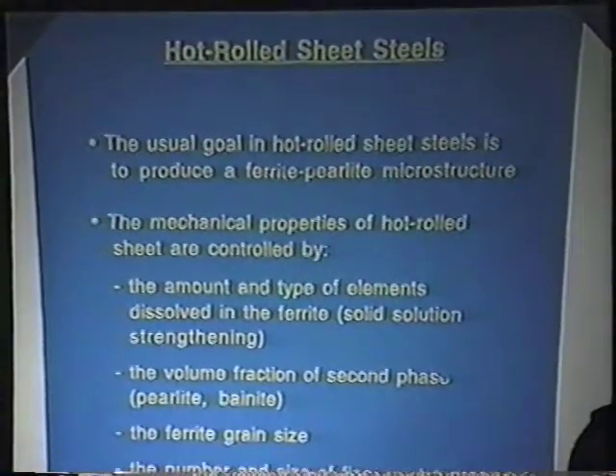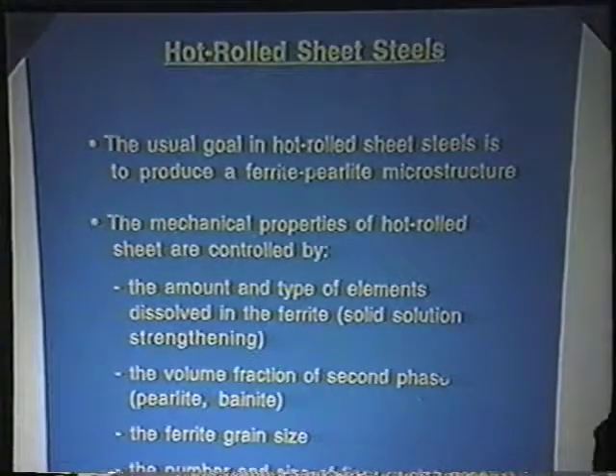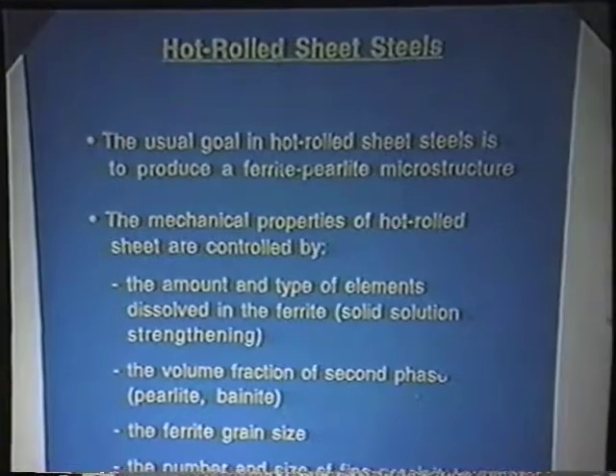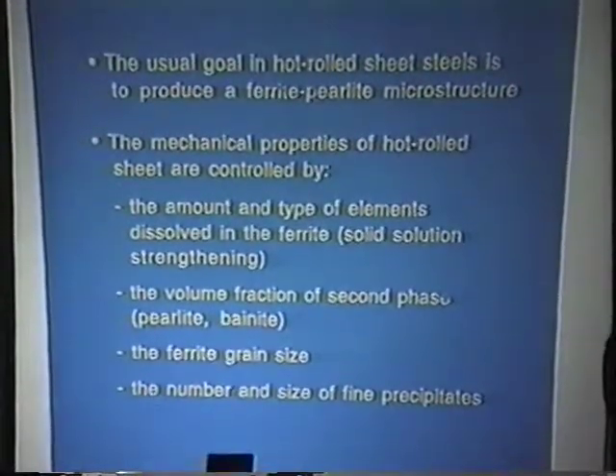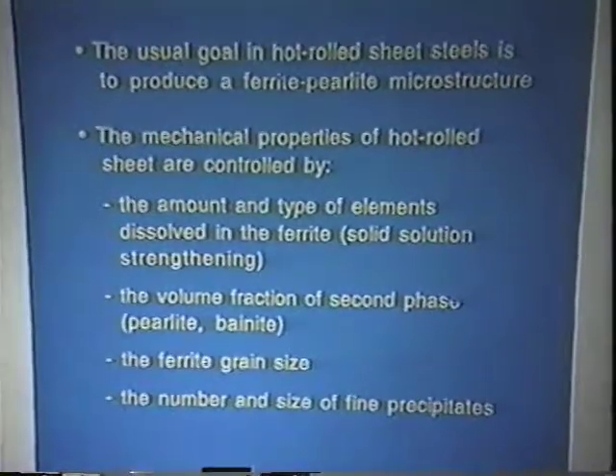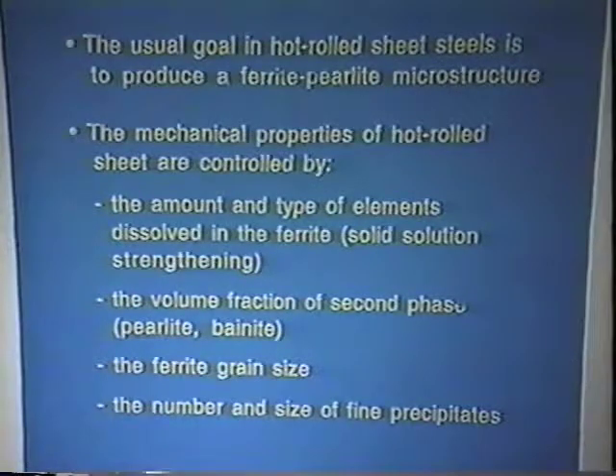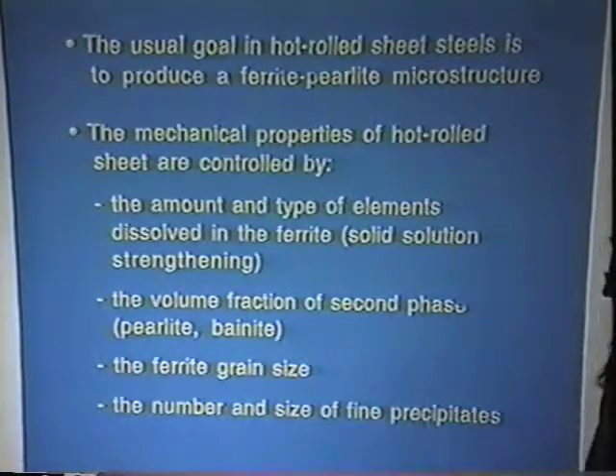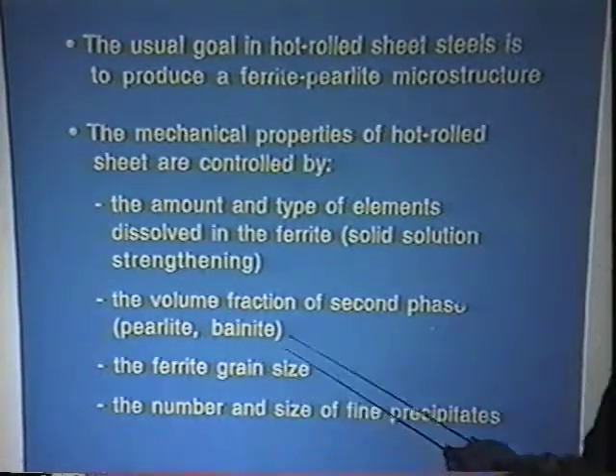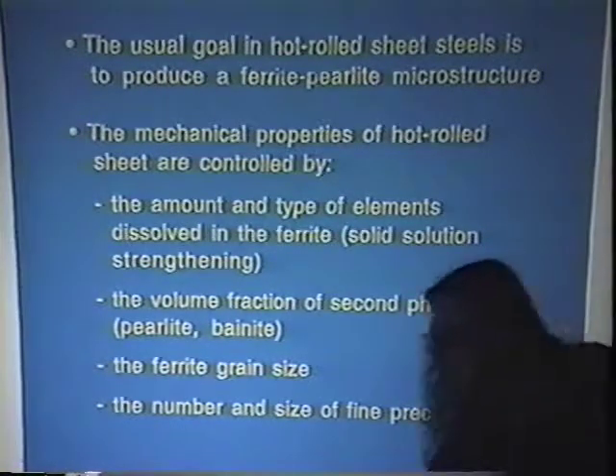Okay, back to college. The usual goal in hot rolled sheet steels is to produce a ferrite-pearlite microstructure. And the mechanical properties of hot rolled sheet are controlled by the amount and the type of the elements dissolved in the ferrite, which, if you're using solid solution strengthened steels, HSLA grades, are manganese and silicon, those type of elements. It's also controlled by the volume fraction of the second phase, where ferrite is the first phase, and the second phase is either pearlite or bainite. Properties are controlled by the ferrite grain size, and then the number and the size of precipitates. If you're using precipitation strengthened steels, that's vanadium, columbium, those type of strengthening agents.